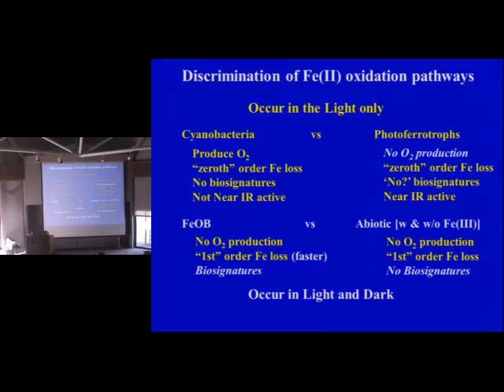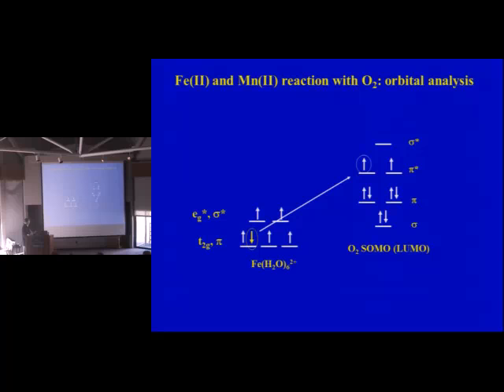The thing is that usually if you have a problem with a reaction, in this case it's a thermodynamic control because the manganese 2 won't oxidize. As a matter of fact, let me do one thing. Those of you that know me, I like to do this. This is the interaction of iron with oxygen. This is a pi electron, t2g, if you know your crystal field theory. And that's a pi star electron. And so what you're doing is you're pumping an electron from iron 2 to oxygen. And this is thermodynamically favorable, but it's also kinetically favorable.